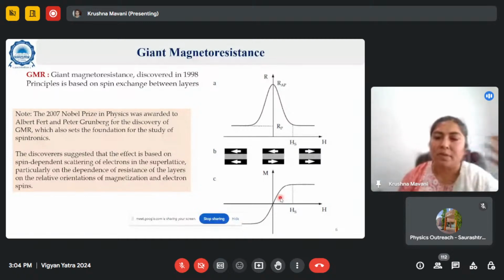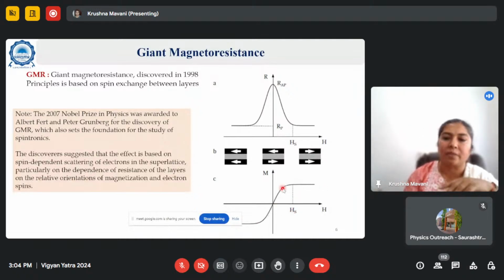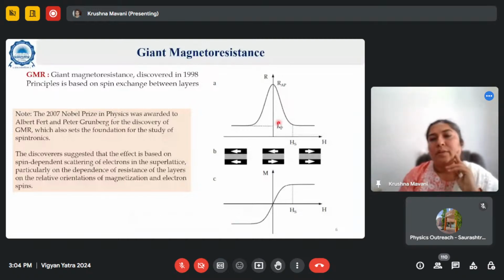If it is a hard magnet, you will see a magnetic hysteresis. I am not showing both the curves here for rising and falling. I am showing only one curve while rising the magnetic field. And then if you see the negative side, you can symmetrically see that the curve is showing saturation of magnetization in the negative side as well. So similarly, resistance on both the ends, when it is saturated magnetization, is very low.